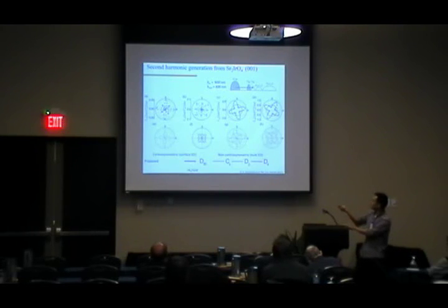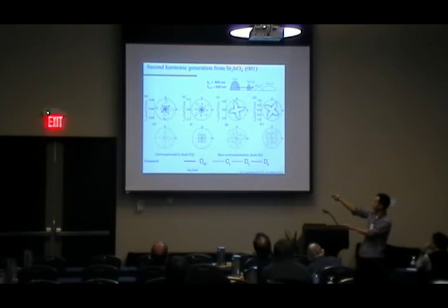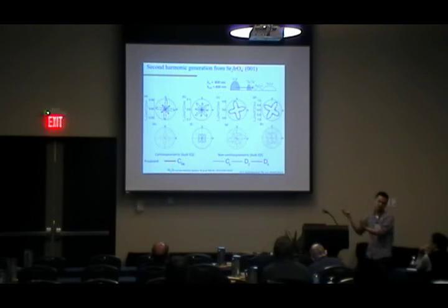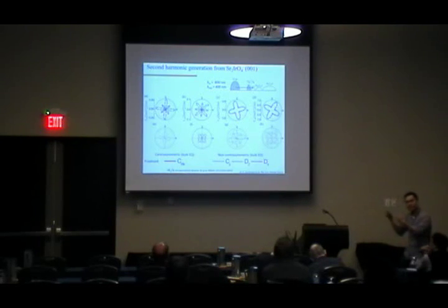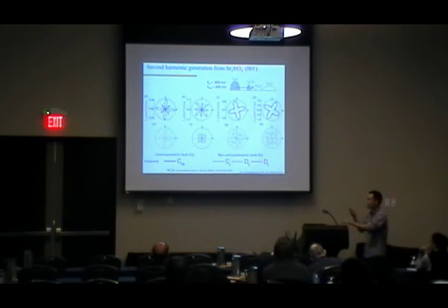This is the original structure that was proposed. That does a little bit better job with our data, but it doesn't do as well for these two patterns. Basically what we find is that there's a symmetry lowering, whereby you remove these so-called CD glide planes. In essence, there's a lower symmetry point group that fits our data rather wonderfully. So this is how we go about doing structure refinement.